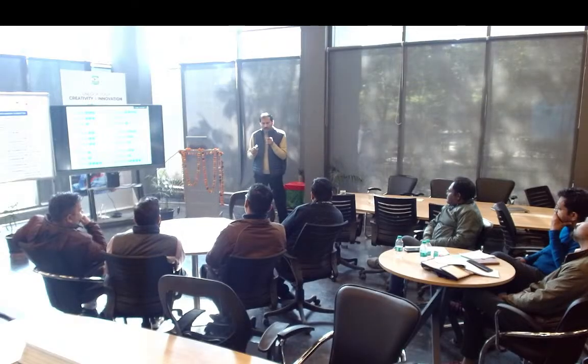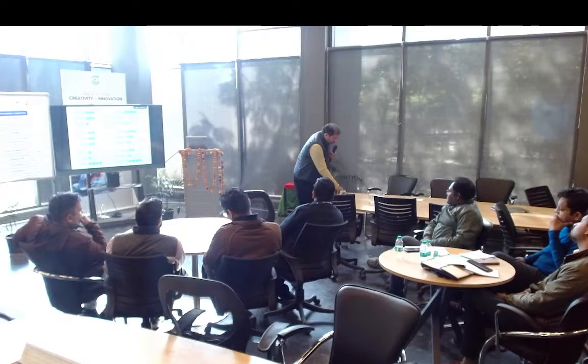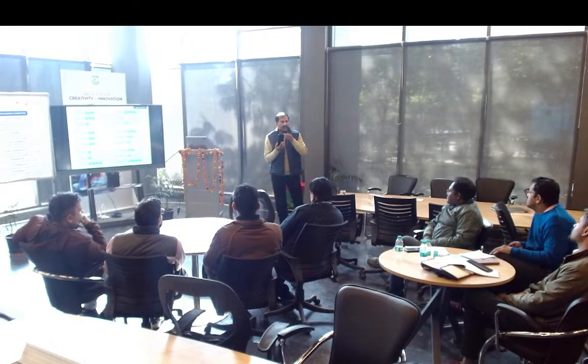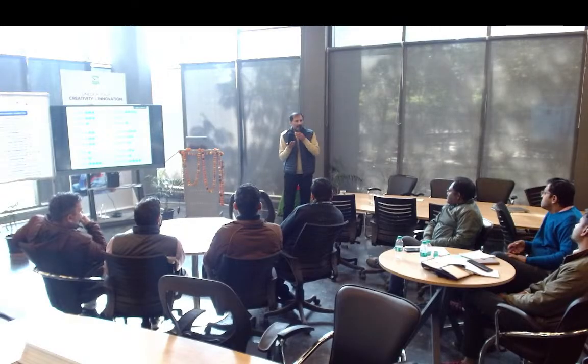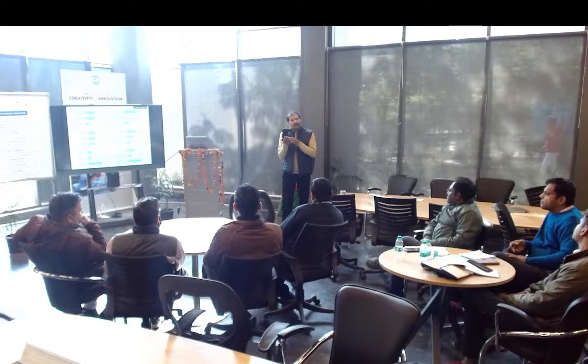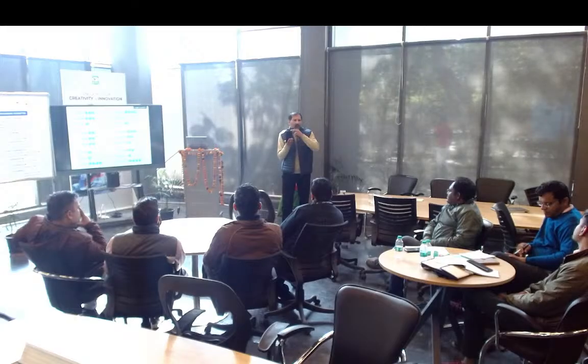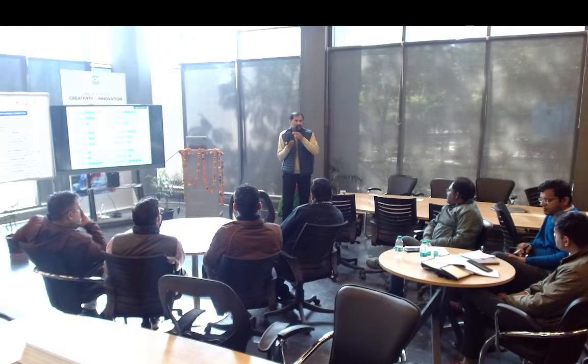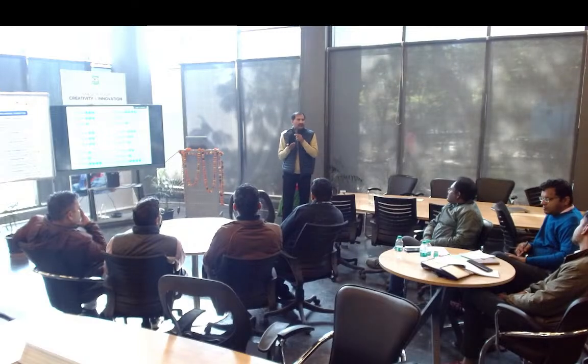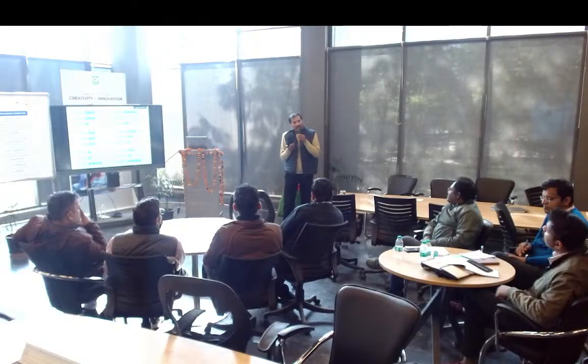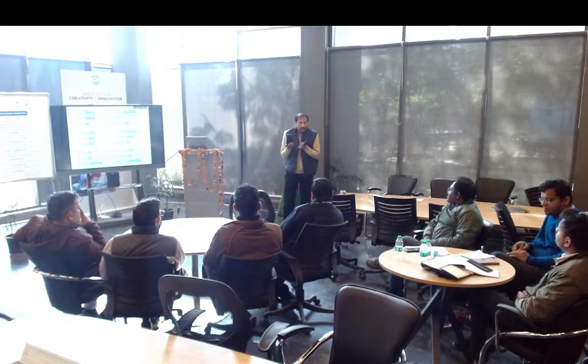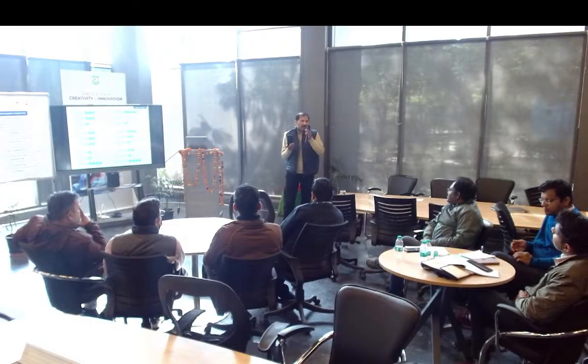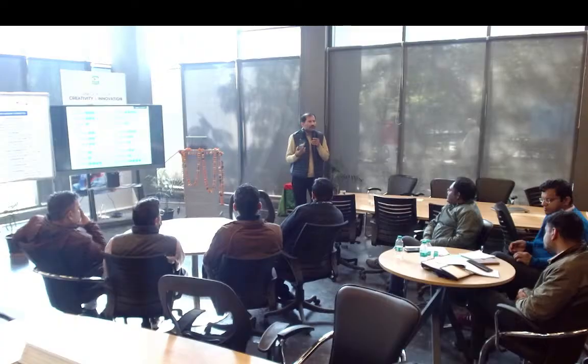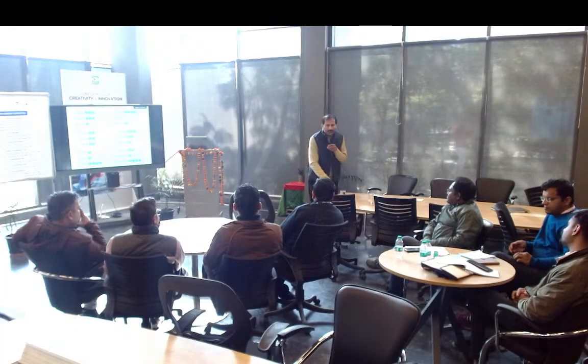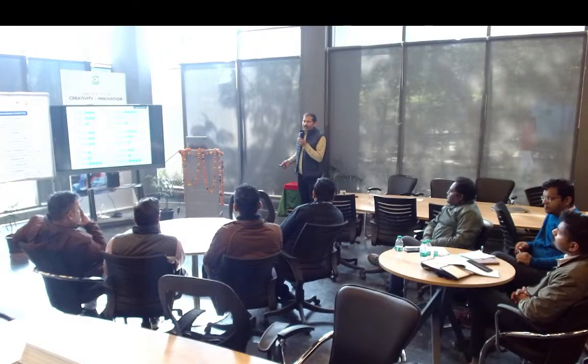If suppose I am producing this part in this orientation, vertical orientation, the number of layers will definitely be high. So the bottom layer which was printed 15 minutes earlier, and now I am at the top. So the temperature of the bottom part is very low, while the top side is around 200 degrees Celsius. This temperature variation can give thermal stresses, and definitely curling and warping will occur at the bottom. So at the bottom either we heat the substrate or do something like this. I will show you some components. So we have to deal with those things. In the third part we will discuss those issues and their remedies.